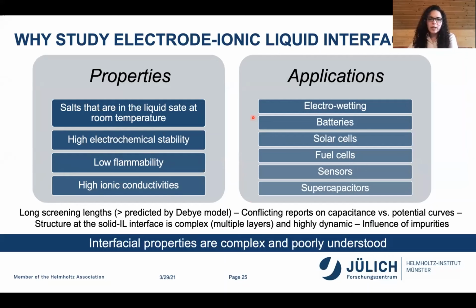But there are a lot of challenges because the interfacial properties are actually very complex and poorly understood. And it's because they have very long screening lengths. Again, we're talking about concentrated systems, so there are a lot of interactions of the ions with one another. And so this already goes beyond what is typically thought of for the Debye model, for example. And we have conflicting reports on capacitance versus potential curves when we're thinking about the interface itself. This is usually a good metric to characterize that interface, but different groups reported different values and different trends.